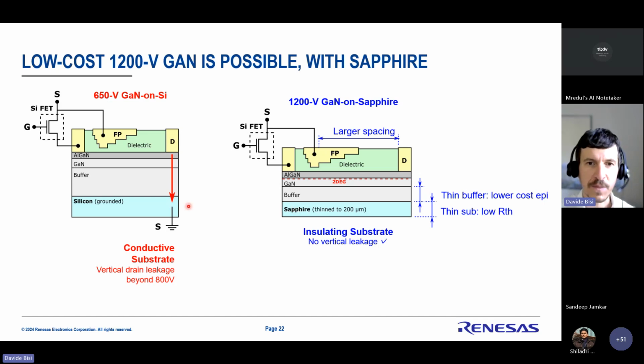So to have the same thermal performance of silicon, sapphire needs to be thinned, but that is okay because sapphire is a very stiff, very hard material, so we can thin it without breaking the wafer. So that's been demonstrated. The second thing is that now the buffer, because there's no leakage between drain and substrate, can be much thinner. So if this one is a few microns, on sapphire it can be less than half of that. So again, we can save on epi time. The epitaxial growth can be significantly shorter on sapphire because we don't need a thick buffer.